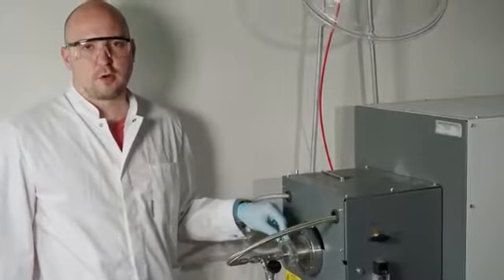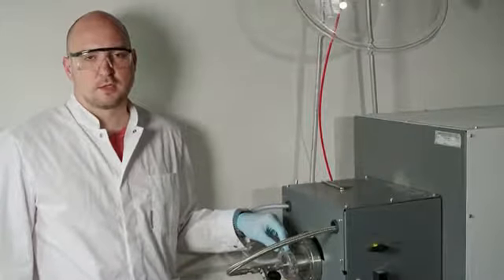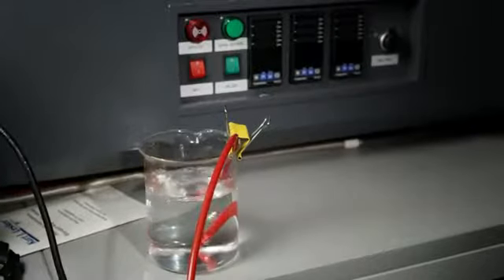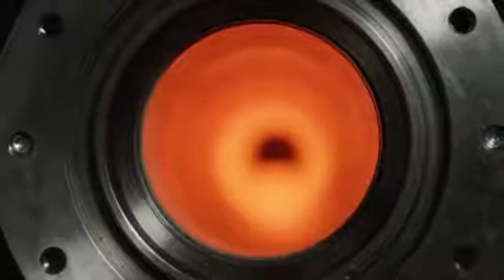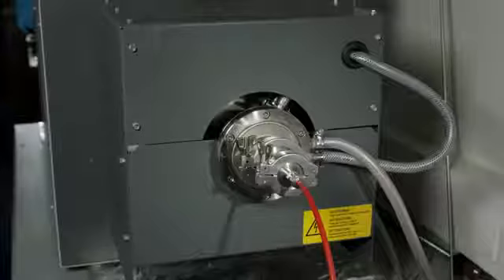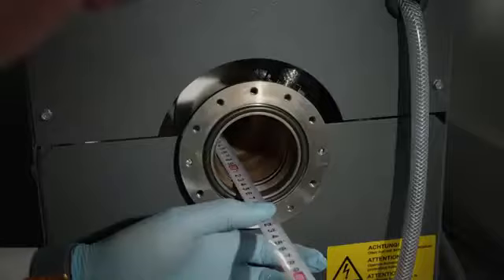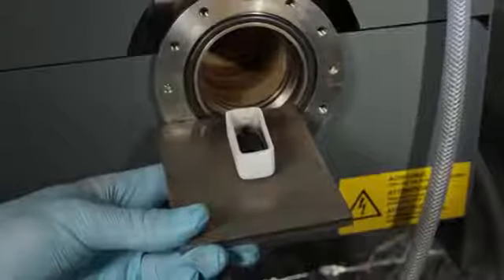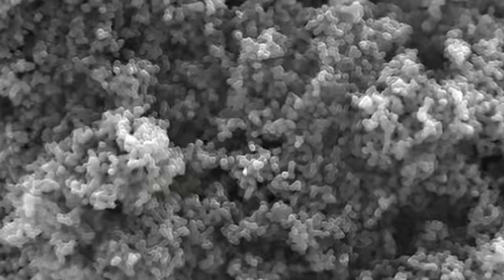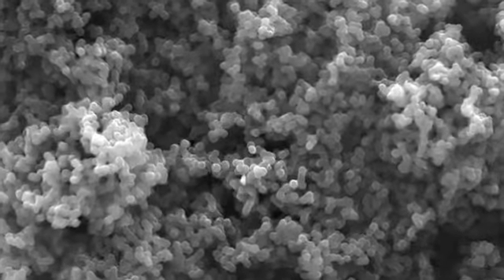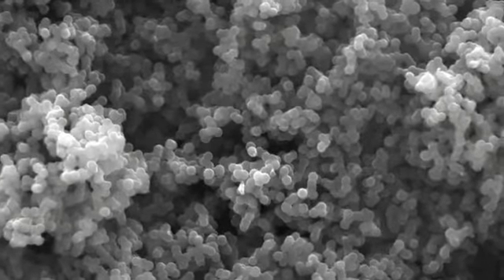Now we're ready to pyrolyze this carbon using this furnace, and we do it in argon atmosphere so the material would not burn. In this process, all other elements are removed from the carbon structure and the carbon becomes further graphitized, which will create more sites for sodium adsorption. Here you can see scanning electron microscopy image of hard carbon material. These particles are spherical with a very narrow size distribution.